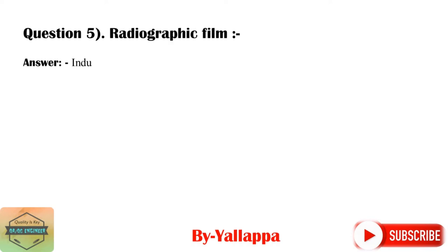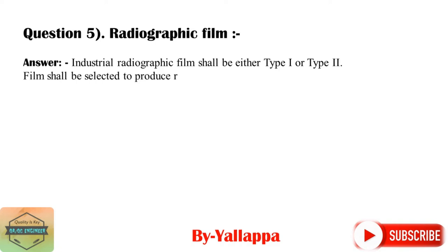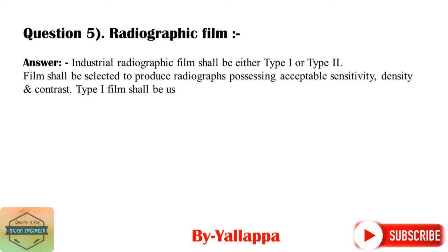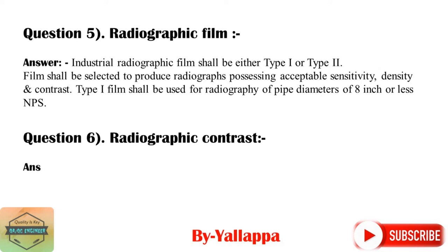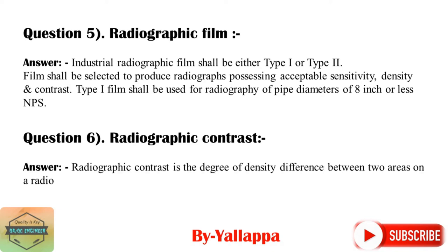Question 5. Radiographic film. Answer. Industrial radiographic film shall be either type 1 or type 2. Film shall be selected to produce radiographs possessing acceptable sensitivity, density and contrast. Type 1 film shall be used for radiography of pipe diameters of 8 inch NPS or less. Question 6. Radiographic contrast. Answer. Radiographic contrast is the degree of density difference between two areas on a radiograph.